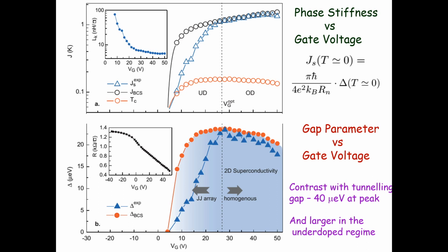So the hypothesis then is, in this regime somewhere, you may have these so-called preformed pairs, which we also talk about in high Tc superconductors, but the full phase-coherent superconductivity appears only in this regime. And here you can say that it is almost like weakly coupled Josephson junctions.